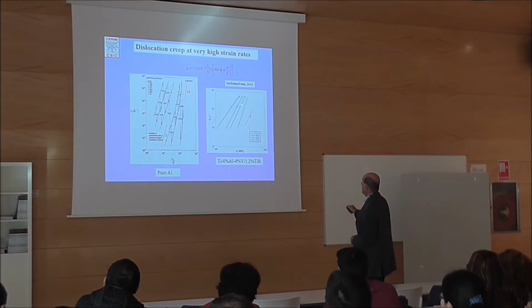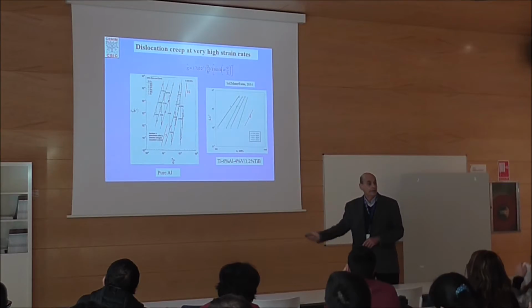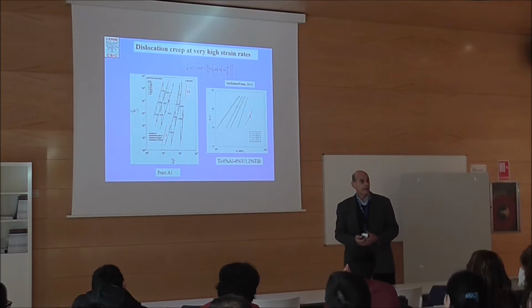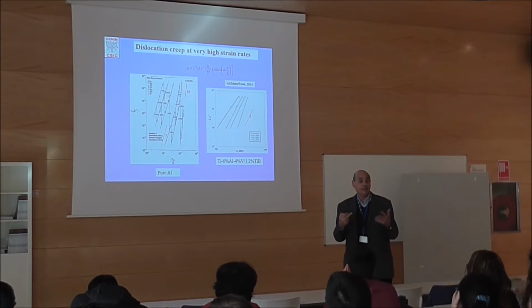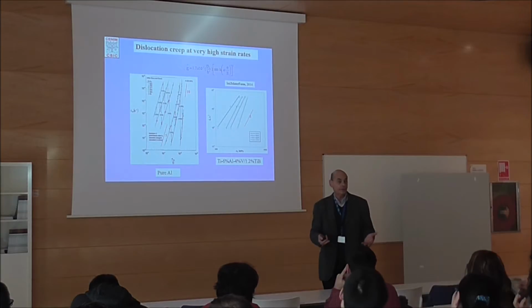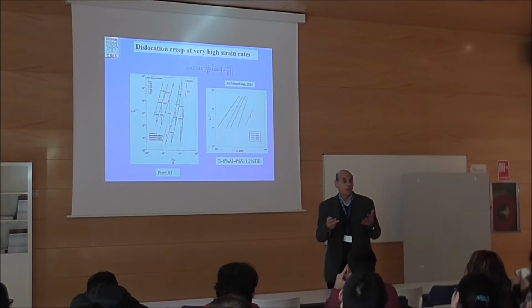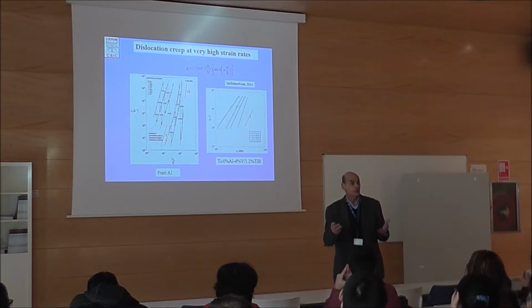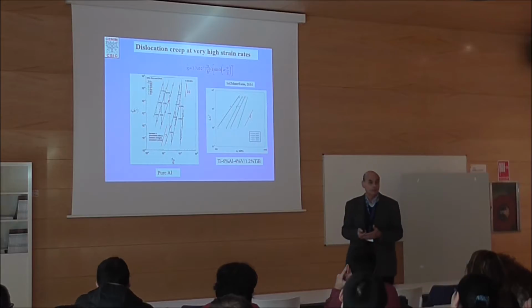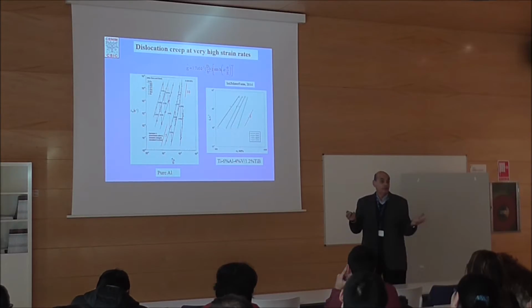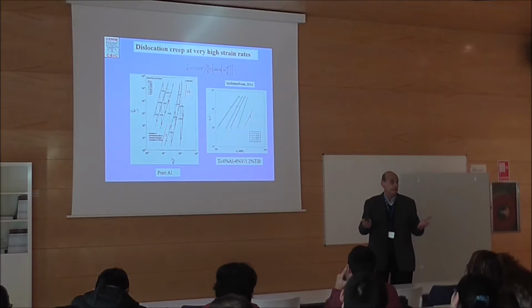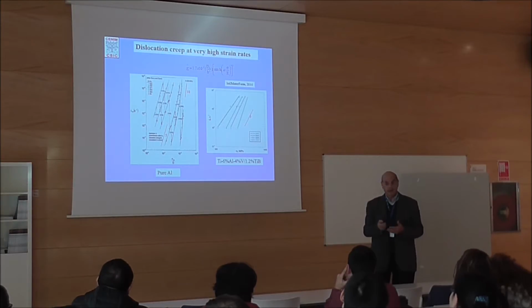It's changing with temperature. This is high temperature, lower, lower, lower. This is 5. This is good for this, but here is 7, here is 8, here is 9. In those cases, we are applying also the hyperbolic sine equation. This is the Garofalo equation. And the basic and philosophical question is, does nature work with a power law, or does nature work with a hyperbolic sine equation? This is something that is still in discussion, so we don't know. But it could also be that a law for nature is not a power law, it's a hyperbolic sine law.